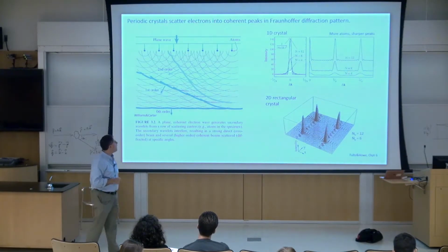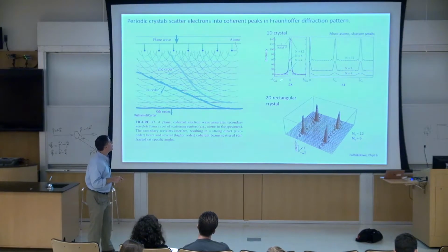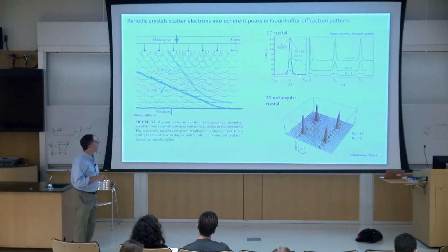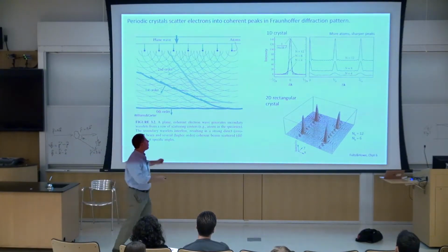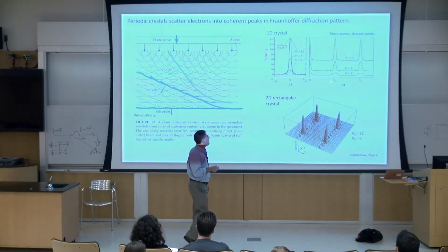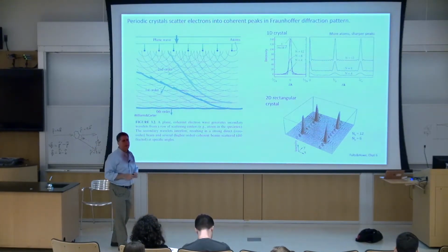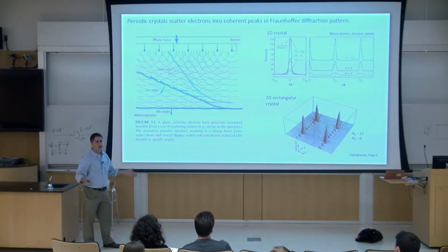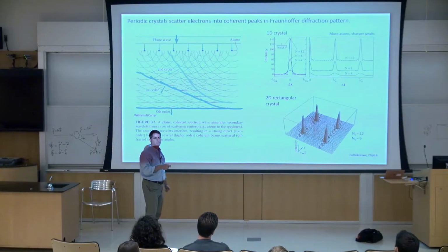And so over here is an example of what the Fourier transform looks like if I had only 4 atoms. It's periodic, but it's limited, and so the diffraction spots end up being quite broad. I would expect a width that would be 1/4 of the spacing between the atoms. And then as the object gets bigger and bigger, if it was 10 atoms wide, then the peaks ought to narrow to 1/10 of the distance between the peaks.